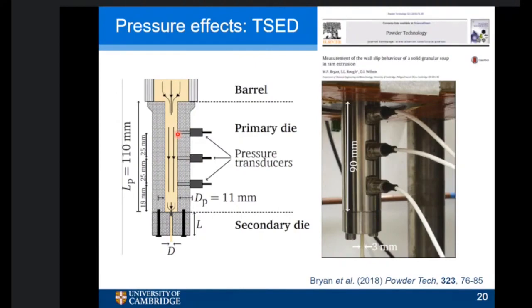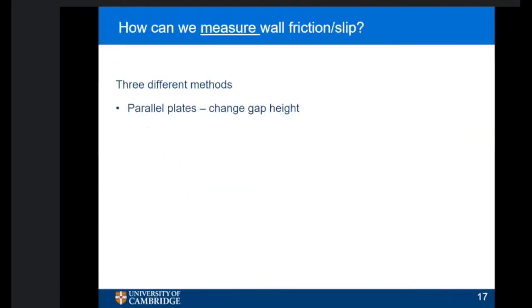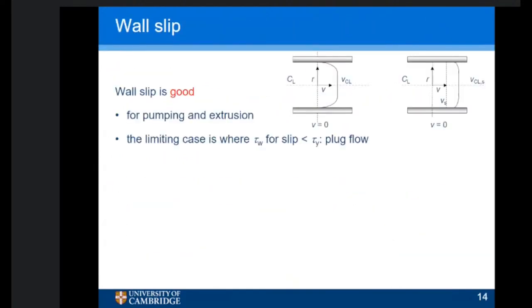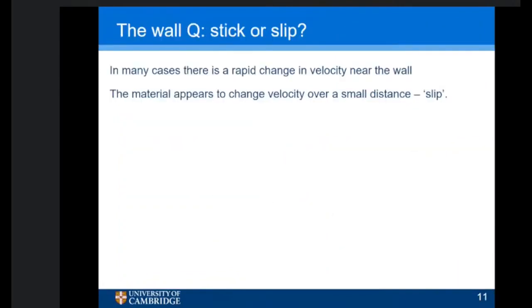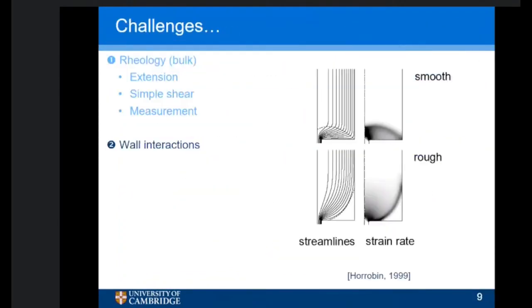We were just given... Another one is we did some work with starch-based paste for making, let's call them, food snacks. And there, because the binder was water, whenever it got enough dissipation, you actually ruptured and denatured the starch. And this comes back to the Horrobin work. If I go back to this plot, you imagine this rough case where you had very high strain rates. That meant you had high local dissipation, and this gave rise to the generation of a film of ruptured starch around the extrudate.